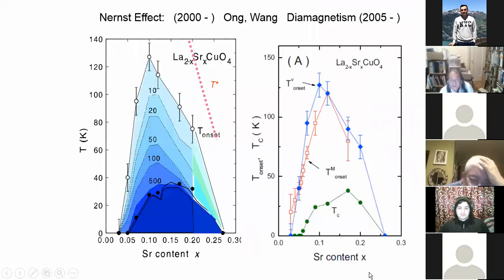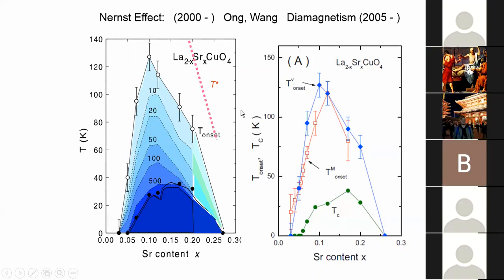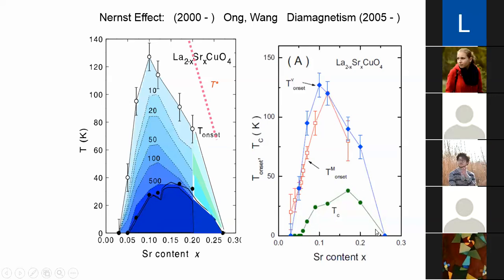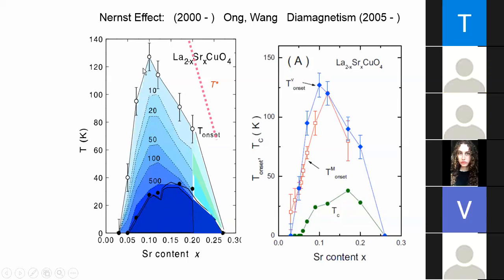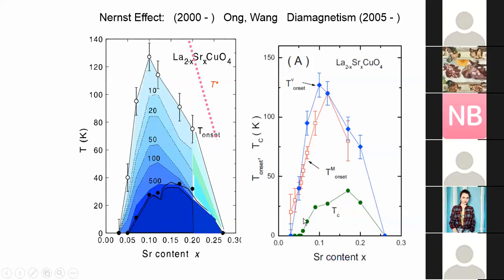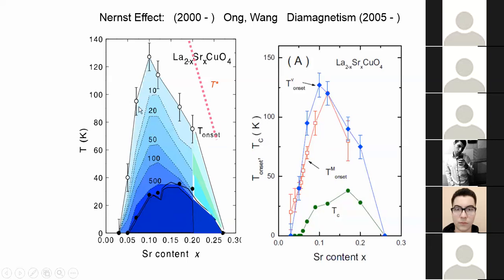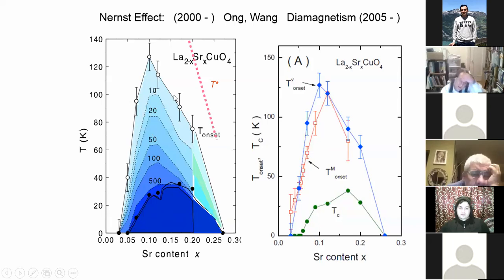Okay. So the third difference has come from, as I mentioned, the observation of the Nernst effect. The Nernst effect is a kind of thermal measurement to measure the motion of superconducting vortices. And so it is usually expected to happen only in the superconducting state. But in some of the cuprate superconductors, copper oxide superconductors, researchers in Princeton found that this TC line is this one, and this interesting Nernst effect occurs at about 4 or 5 times higher temperature, especially in the so-called underdoped region, the region where the TC is increasing with charge doping. You're seeing that this Nernst effect shows up at a very high temperature.